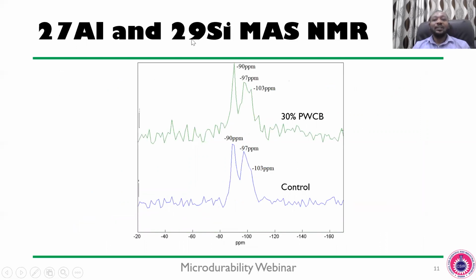So we did the microstructural analysis using the NMR, Al and Si NMR. But for the purpose of time and the presentation, I'm just limiting myself to the Si NMR. So this is the control. The point of interest is at -103. You see that there's nothing happening here, but when you come here, we see that there is a little bit of a peak. Now this peak is very significant to the study of polymerization. So we can conclude that what is happening here means that calcium silicate hydrates are being formed. And that is the more reason why we had the 30% mix having higher strength than the control.